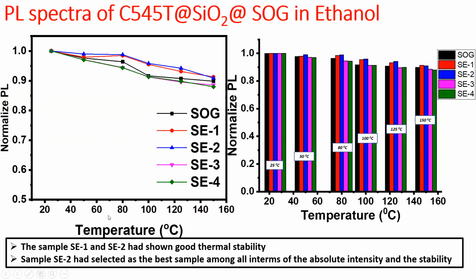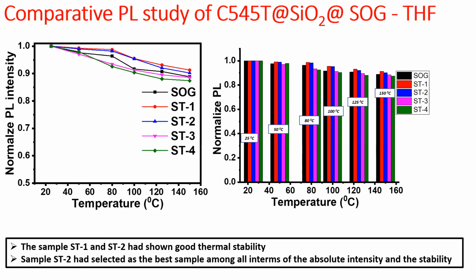Here is some result I am showing very fast. I took different solvents, like ethanol, even though C545T is soluble in THF, not ethanol. I just checked how it works. It was okay up to 80 degrees centigrade. This is a stability curve: uncoated C545T degrades to around 92%, but the coated C545T shows almost no degradation at all. Up to 80 it is good, and with time it is still okay, but at 160 my material is also not able to keep it safe. The target was up to 110, and up to 110 I could successfully make it more stable. This is in THF, and in THF I got even better results.